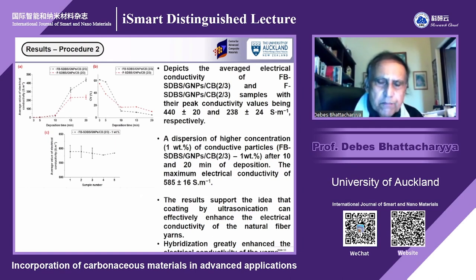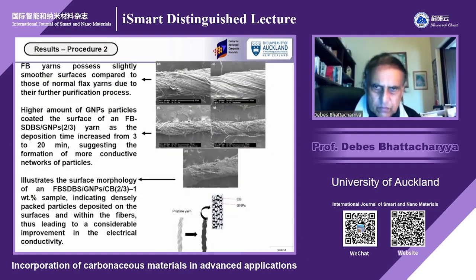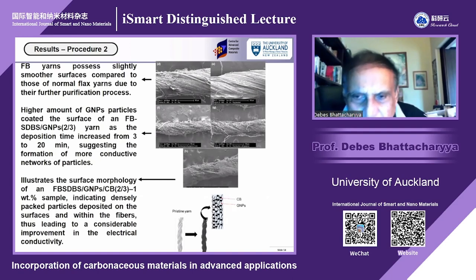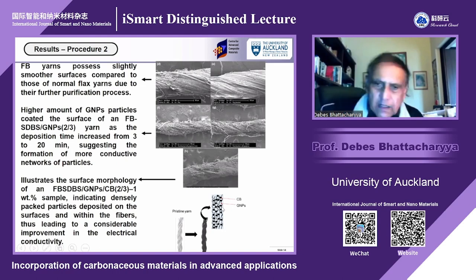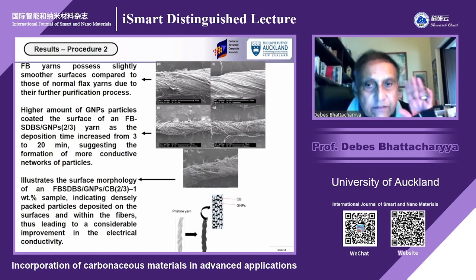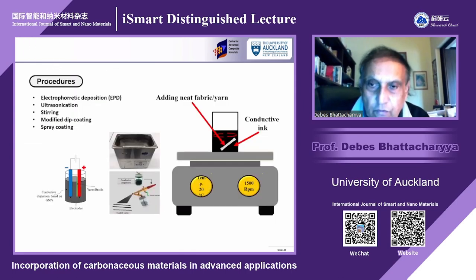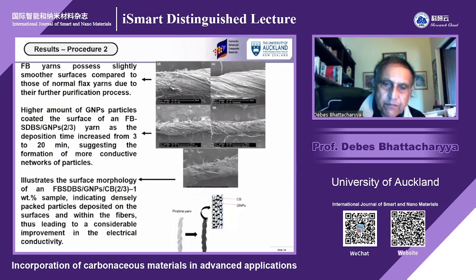Once we got that sort of fabrication procedure more or less under control, we thought, let us have a look at that fiber yarn, what has happened. It is very interesting. Whether you can see or not, I have shown schematically that you can see the carbon black particles have gone inside there, and the GNPs are there, and all these GNPs are aligned in the longitudinal direction. Exactly as we explained a few slides back, the carbon black has gone inside those nanoplatelets, and the fabric has become black from the deposition.